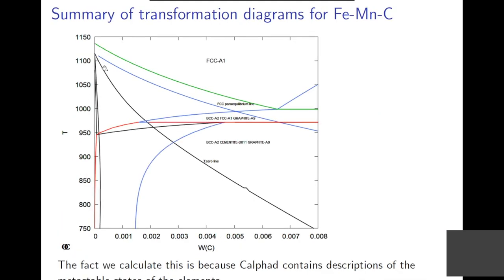And then I put it all together. So you can see the stable diagram is the one with this line. The para-equilibrium line is of course inside the two-phase region because it's metastable. So if you cool down FCC into the para-equilibrium line here, you can have a very rapid diffusion of carbon away from the FCC and forming BCC with a different composition here. And if you cool it down below the T0 line, you can have martensite or other forms of carbide structures. So having this information, you can calculate lots of possible metastable transformations.